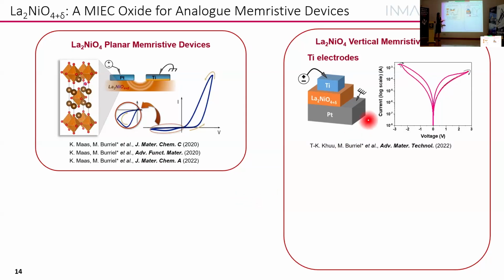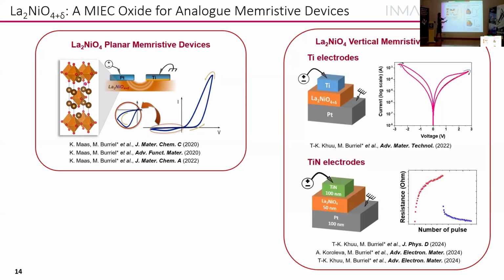We also obtained some nice memory resistive switching curves. You see here the high hysteresis, the 2 states. However, it was not very reproducible. We believe that is because this titanium gets oxidized at the interface, but we were not able to control it in a reproducible way. So in the second part of his PhD, he moved to titanium nitride. And since we moved to titanium nitride, we really have very reproducible results for these type of devices.